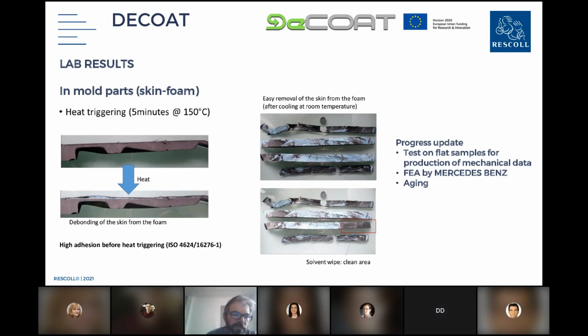You can see on the left picture, from the top to the bottom, the peeling, the self-peeling, self-stripping of the PVC foil. So it's easy to remove the old PVC foil from the PU strip. And you can see on the bottom picture on the right that you can easily clean the light blue area with solvent. So it's nice, promising results to think about the possibility to recycle on one side the PVC and on one side the PU foam.